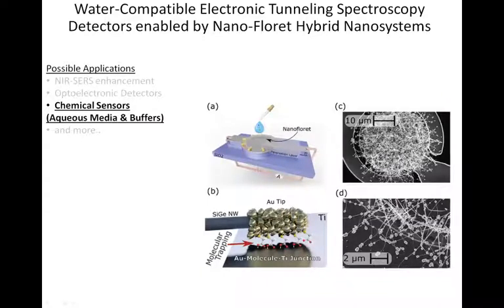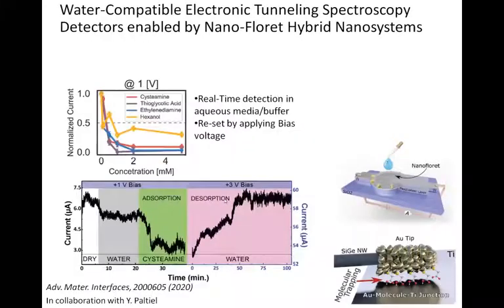Next, we wanted to utilize the same concept, but for liquids. So here we changed the design. Instead of having this tip design, we wanted to have large surface area. So now we have a concentric design where we have a central electrode. You can see an SEM image here. And these nano-florets contact the counter electrode, which is concentric. We add a passivation layer, so it will be operable under liquids and so on. And this is what you get.